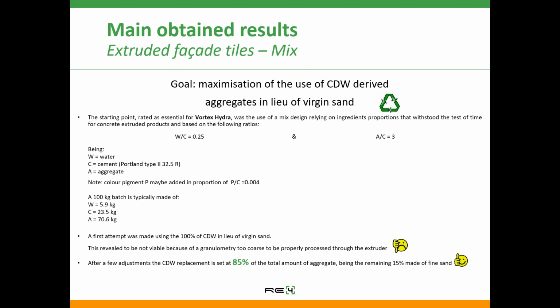As a goal, we had the maximization of the use of CDW derived aggregates in lieu of virgin sand. We used a mix design that we were familiar with, with a water cement ratio of 0.25 and an aggregate cement ratio of 3. As a hydraulic binder, we have used Portland cement type II 32.5. And we have been able to reach an 85% replacement rate, which is very encouraging. The last 15% was made of fine sand because of the rough granulometry. It was not possible to process the full replacement material, where CDW derived aggregates were the substitution element for virgin sand.